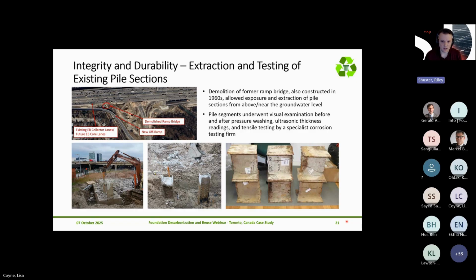And as Lisa's highlighted, on this project, there was demolition of a former ramp bridge, which had similar service life as the structure that we're trying to reuse, which provided an opportunity to extract pile segments. So those pile segments shown here were subject to visual examination both before and after they'd been cleaned, and then ultrasonic thickness measurements were collected by a specialist corrosion testing firm to provide an opportunity for site-specific data. Next slide, please.